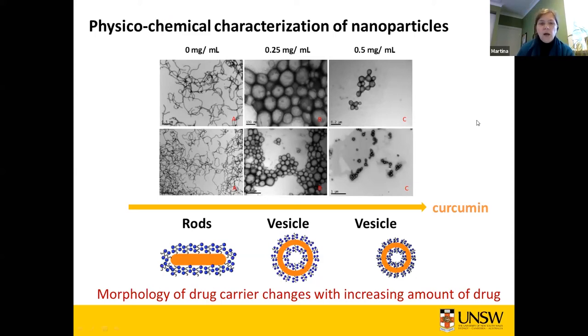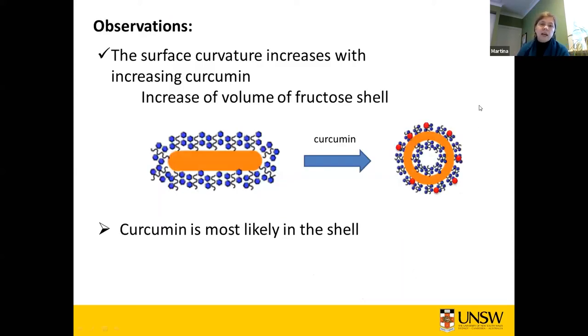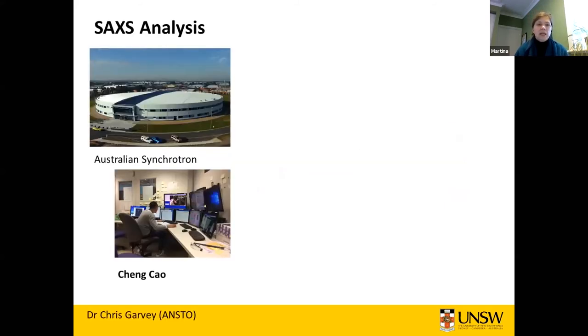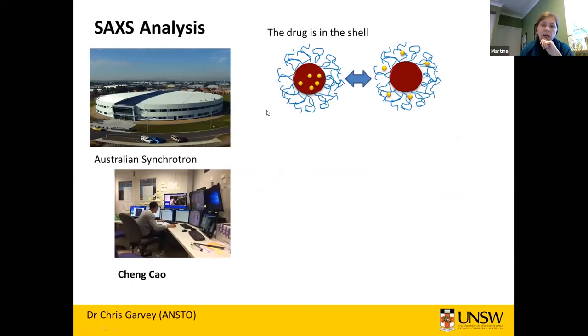So again, we need to really investigate now what happens with these nanoparticles. And we can sort of see already from the way the relationship between self-assembly and drug is progressing, that the drug is probably sitting in the shell, but you can confirm this using, again, X-ray scattering. And the result from the X-ray scattering is that the drug actually, when it was sitting there, leached slowly into the shell. So the drug wasn't in the core at all. Although it was a hydrophobic drug, and hydrophobic drugs should be in the hydrophobic core. So it leached into the shell.